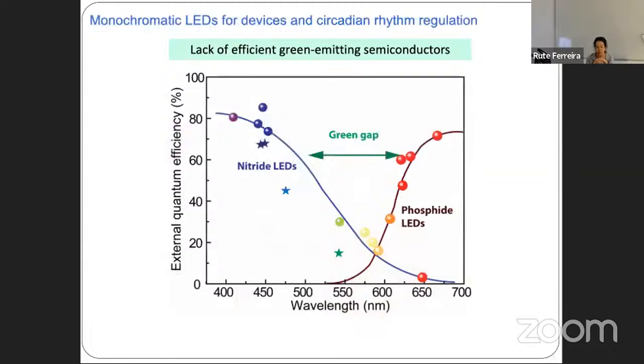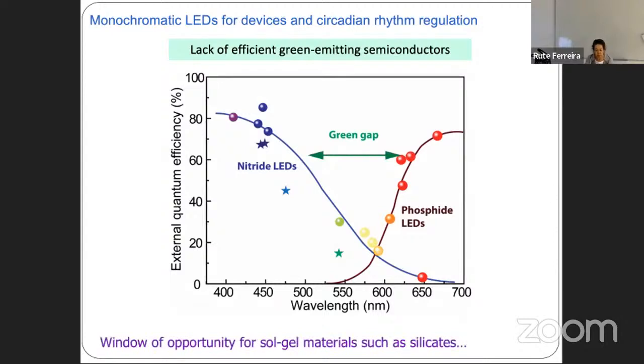So the green gap issue appears due to the lack of efficient green-emitting semiconductors. This graph shows the external quantum efficiency as a function of the wavelength, and we can clearly see a drop in the efficiency in the green spectral region. So in parallel with the need to develop white light emitting sources, there is also a need to develop green emitting materials for solid state lighting. And here I bridge directly with the examples that I want to show to you.